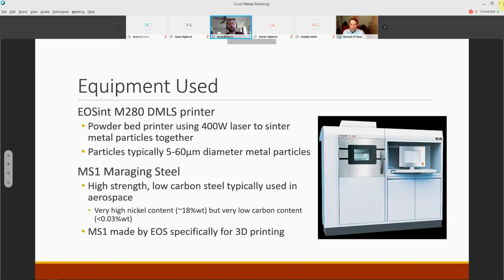For the equipment, we used our school-supplied EOSINT M280 direct metal laser sintering printer. It's a powder-based printer with a 400-watt laser and particle sizes of 5 to 60 microns. We got the machine at the school through a grant, and we got it up and running this year with MS1 maraging steel, which is a high-strength, low-carbon steel used in aerospace applications. The MS1 powder is made specifically for the EOS printer by EOS.